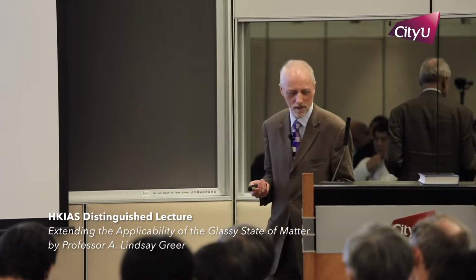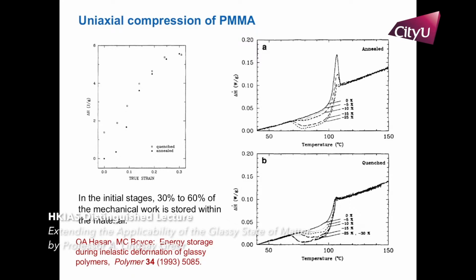Should we be happy having found that number for the metallic glass? Well, probably no. We should probably be disappointed, because if you took a different glassy or amorphous material, namely a polymer, and you were to do a similar experiment, you'd store 30 to 60% of the mechanical work as a result of changing its shape. Why is the metallic glass so bad?